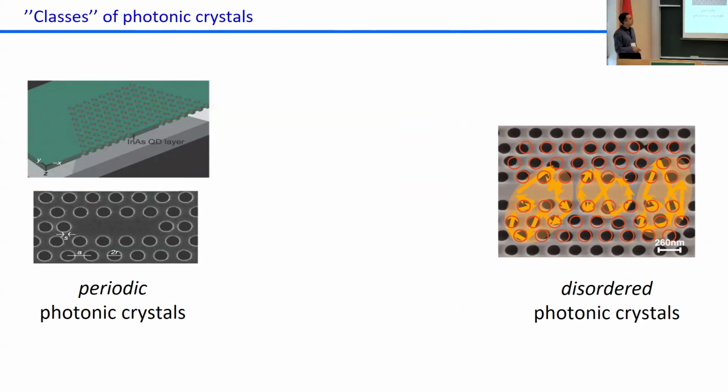which is something we have been working on in the past, which is, for instance, in this case, a photonic crystal waveguide. So we have removed a row of holes. We have a sort of one-dimensional system for the propagation of light, but then we introduce disorder by perturbing the position of the air holes with respect to the perfectly periodic structure, which is shown by the red circles. So the fabricated holes are randomly distributed around the position where they should be in the perfectly periodic system.